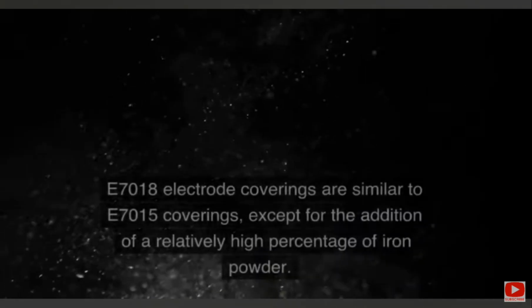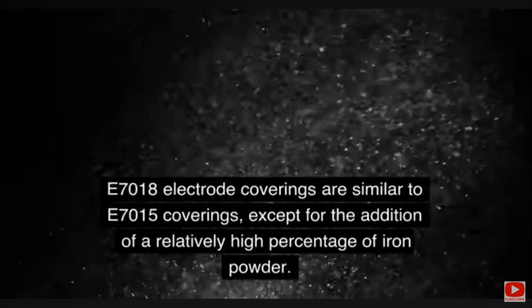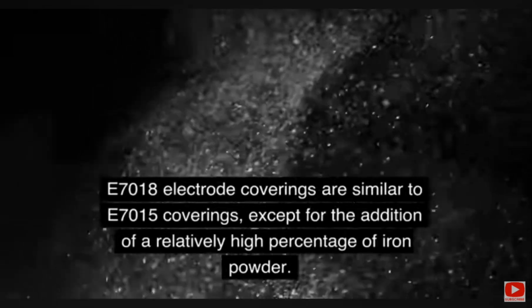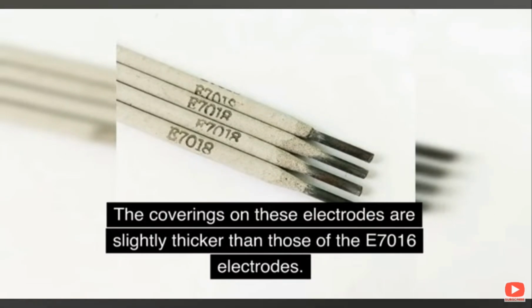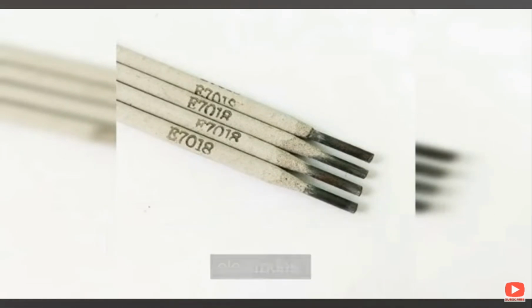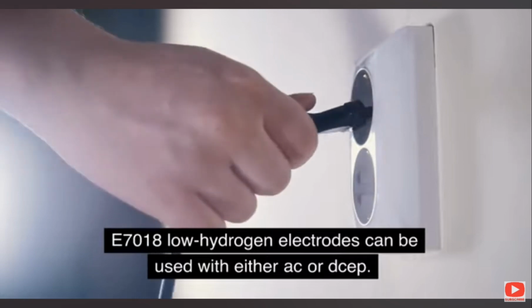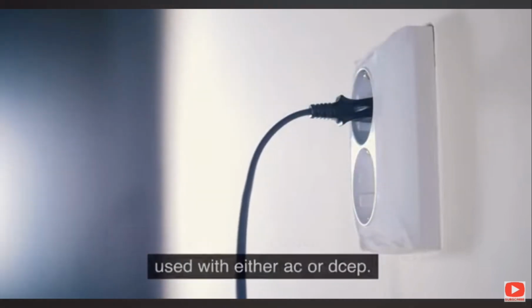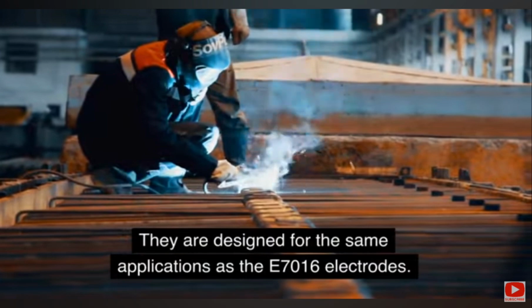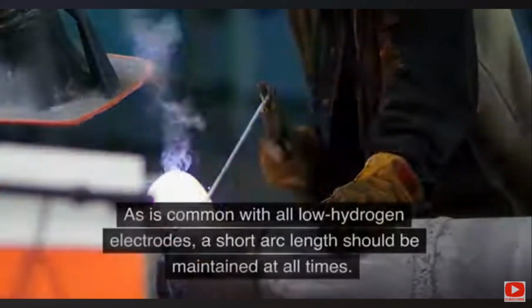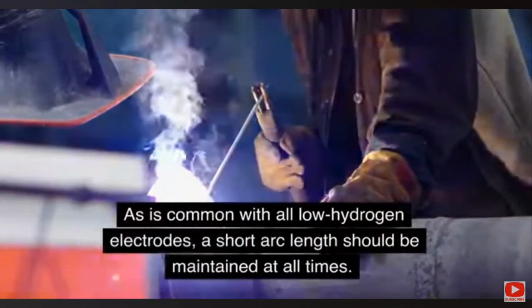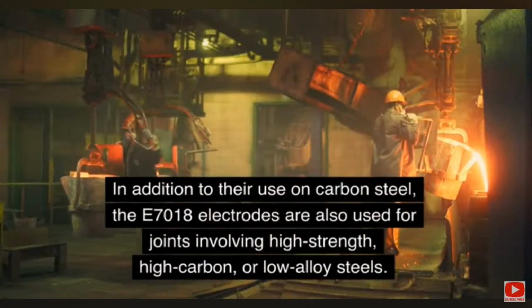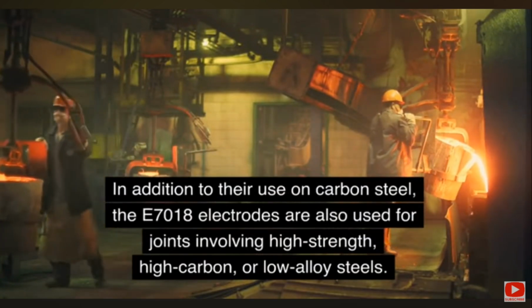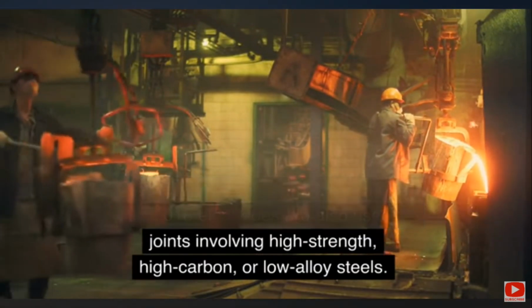E7018 welding rod. E7018 electrode coverings are similar to E7015 coverings, except for the addition of a relatively high percentage of iron powder. The coverings on these electrodes are slightly thicker than those of the E7016 electrodes. E7018 low hydrogen electrodes can be used with either AC or DCEP. They are designed for the same applications as the E7016 electrodes. As is common with all low hydrogen electrodes, a short arc length should be maintained at all times. In addition to their use on carbon steel, the E7018 electrodes are also used for joints involving high strength, high carbon, or low alloy steels.